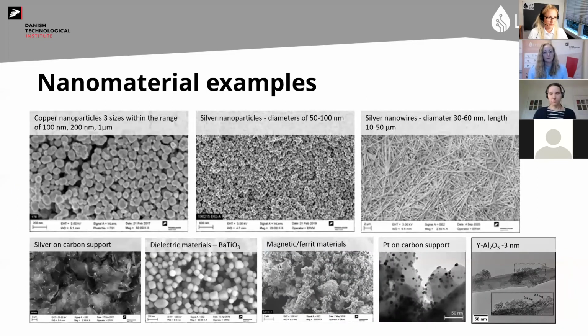Here are some examples. Here are some SEM images of different materials we have been making. And the three big pictures are the ones that we mainly use for printing electronics. So here we have the copper as the first one. And we usually work with 3 different sizes in the range of 100, 200 and more nanometers to 1 micrometer, depending on the application, which I will come back to. And we also produce silver nanoparticles in diameter between 50 to 100 nanometers. And then we also produce silver nanowires with different diameters and length.